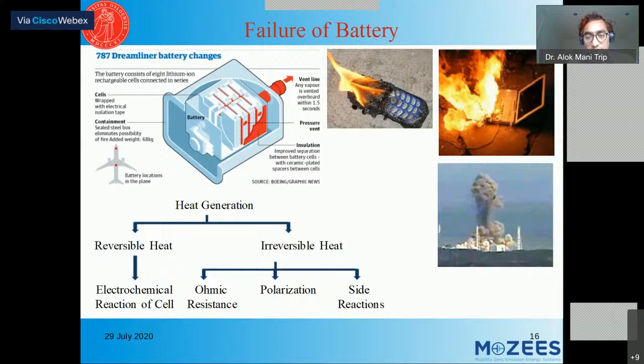Then we have polarization, because when ions try to come out, because of the free energy issues which are required to move the ions into the electrolyte, and then the problem at the interface, this polarization is increasing. This is also contributing to the energy. This is also kind of a resistance, but it's fully faced by the ions.